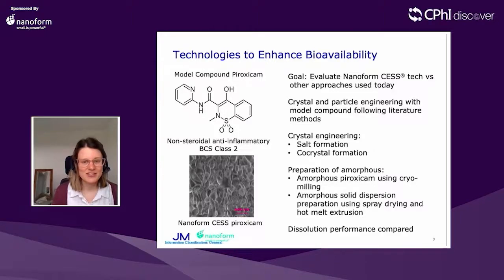So in terms of crystal engineering, we looked at salt and cocrystal formation. And then we also looked at preparation of amorphous piroxicam using cryomilling, and then also amorphous solid dispersions of piroxicam using both spray drying and hot melt extrusion. And then following on from this, we then compared the performance of those different particle and crystal engineered particles using a dissolution comparison.